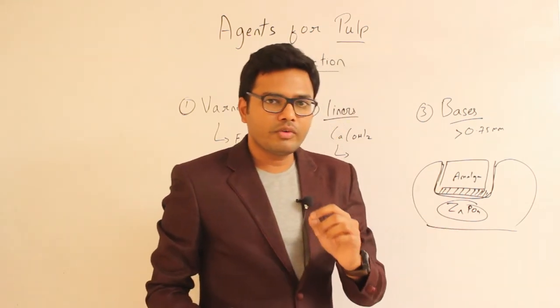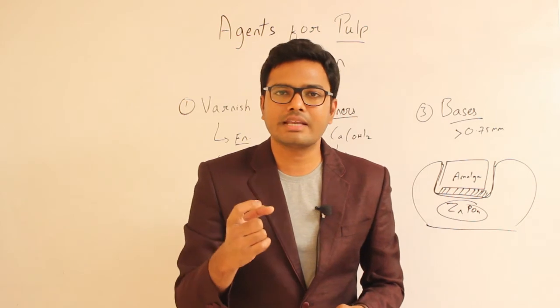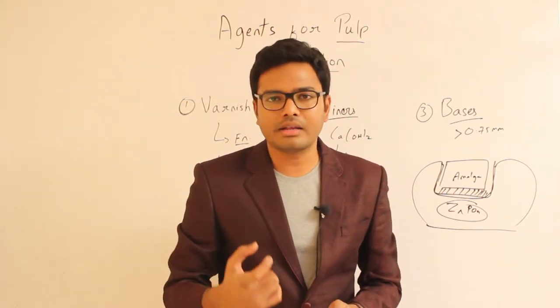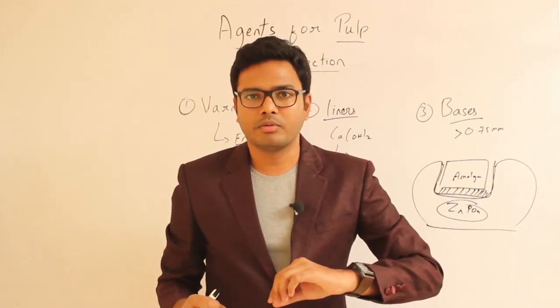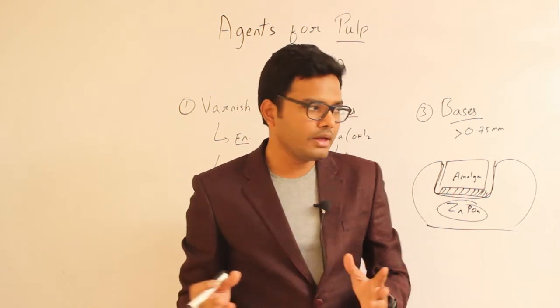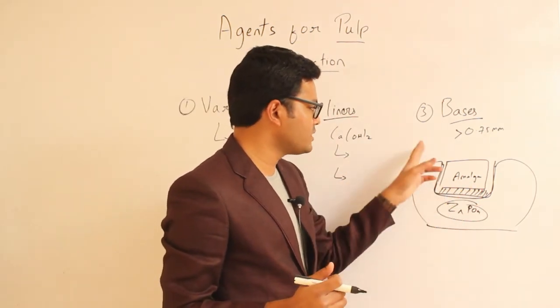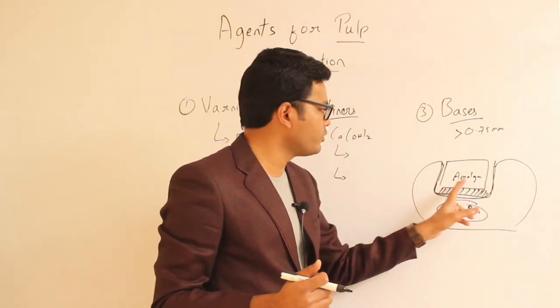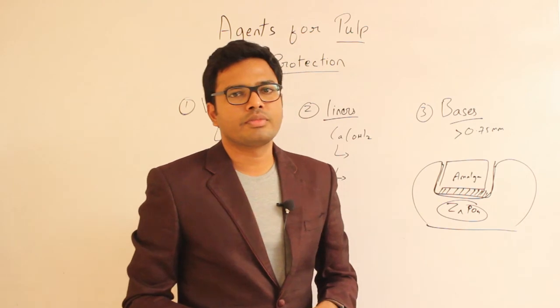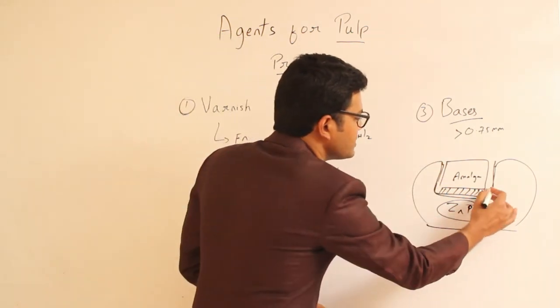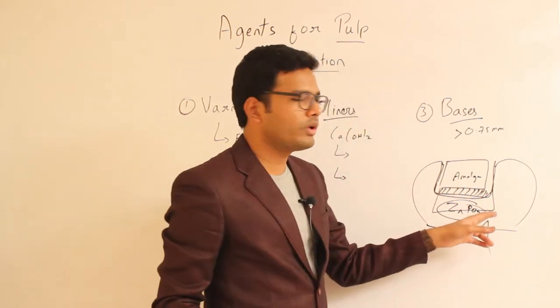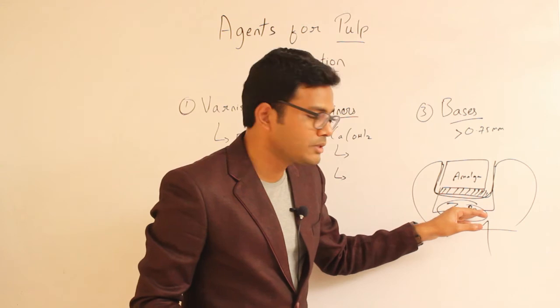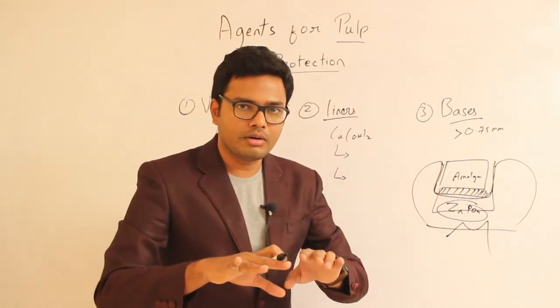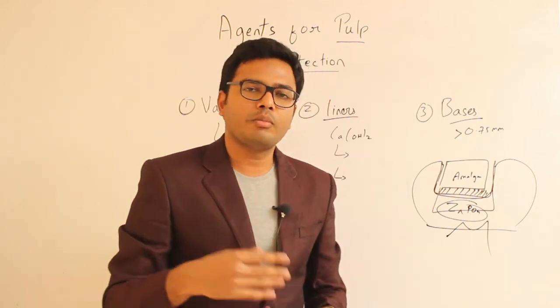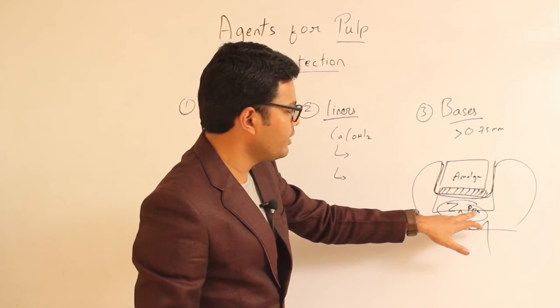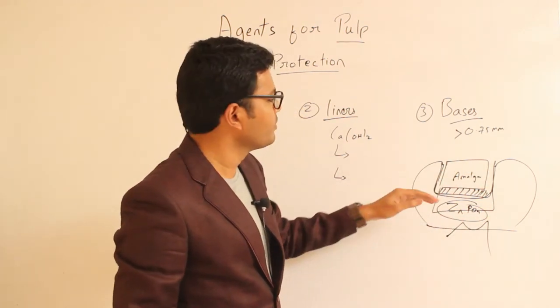But keep in mind, the moment we mix zinc phosphate to such an extent that it is less tacky and dull in appearance, it means less free acid is available, so that will be least irritating to the pulp. Apart from that, while we are regularly placing zinc phosphate cement, it's always advisable to apply varnish followed by zinc phosphate base and then followed by amalgam restoration. What if the cavity is deep? If the cavity is deep enough, close to the pulp, then we'll be placing a liner. First we place a calcium hydroxide liner in order to have some beneficial activity like formation of reparative dentin. And after applying calcium hydroxide, again we go with the application of varnish followed by base and then followed by restoration.